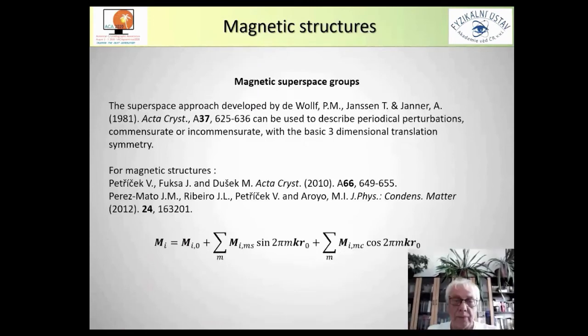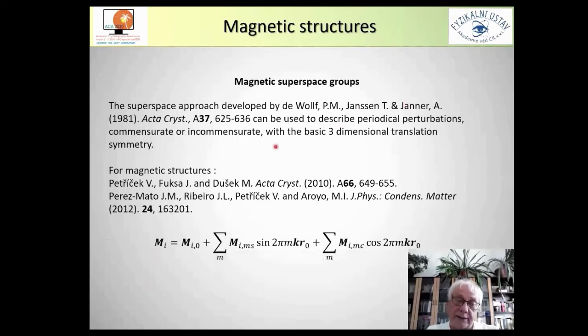For description of magnetic modulated structures, we can again use the superspace approach as developed by de Wolff, Janssen, and Janner. But here we have to take into account that our magnetic moment is an axial vector, and moreover that each operation can be combined with the time inversion operator. This was described in these two papers. Magnetic moments can again be expanded into a Fourier series, where we have this zero term, sine terms, and cosine terms.